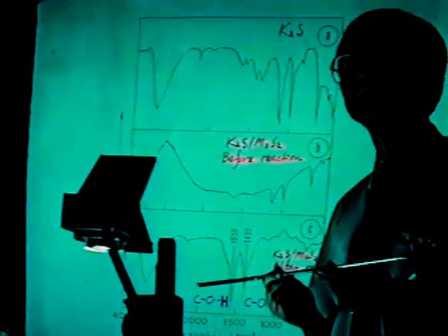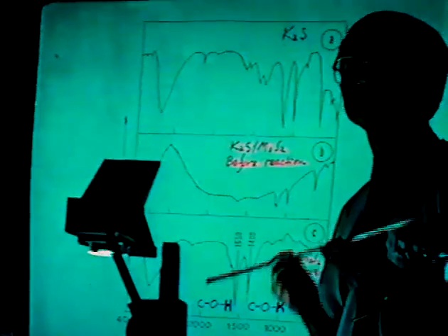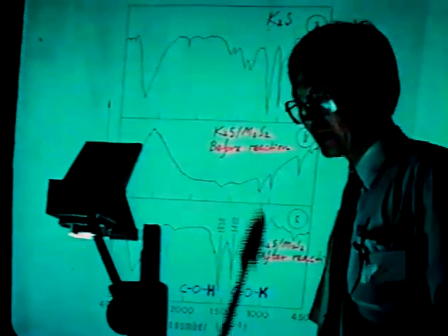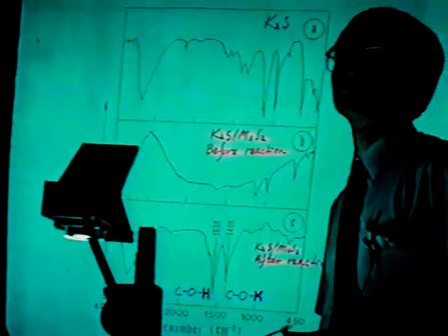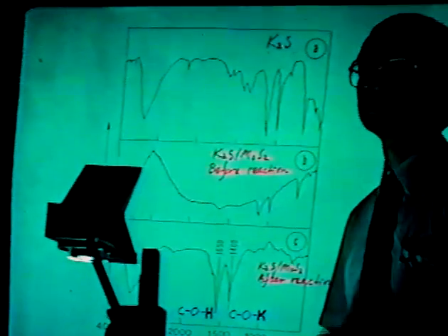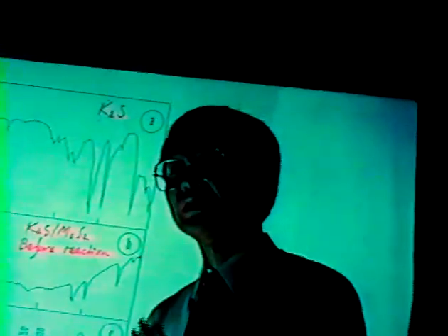In fact, all the alcohol promoters show these characteristic two peaks irrespective of their initial state. So it seems that the alcohol promoters not only distribute uniformly on the surface, but also form a common intermediate, which must be an active species for the reaction. On the other hand, chain growth promoters maintain their initial chemical state and seem to aggregate with themselves or show a very poor distribution.